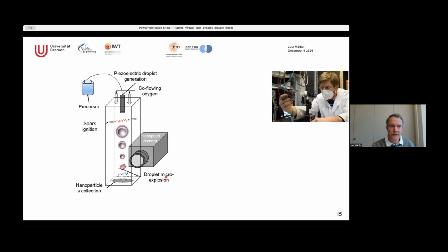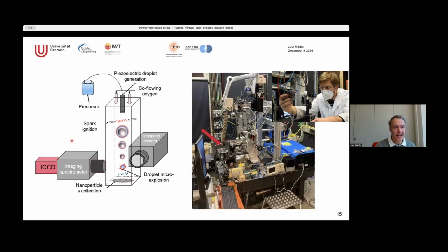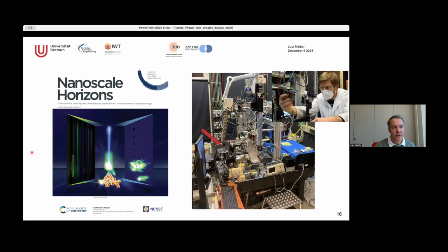So Jan has a similar single droplet reactor, but he has his droplets falling down. He has one very specific setup where you have a camera, and with this camera you can actually look at the spectroscopic lines of these different metals. And with this, he can have a look at which metal is actually coming out of the single droplet. And as we expect, we really want both metals coming out at the same time when we make lithium titanate, for example, because we need to atomically mix them.